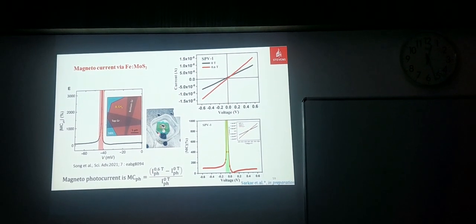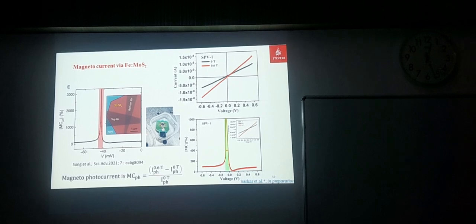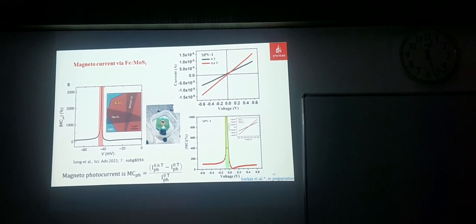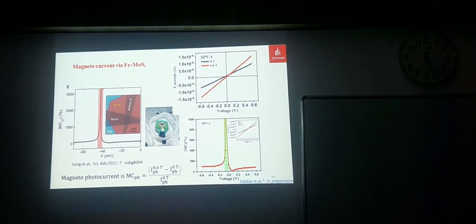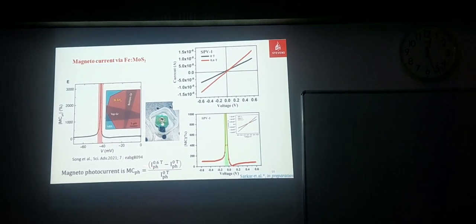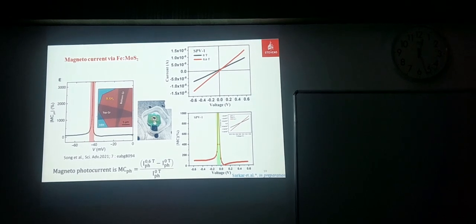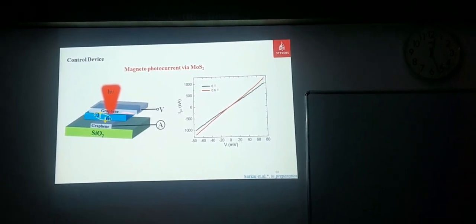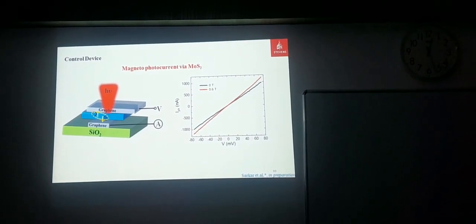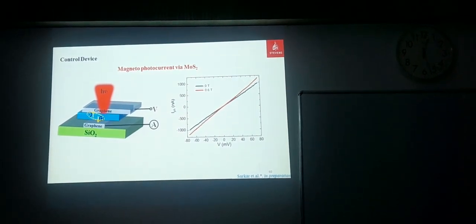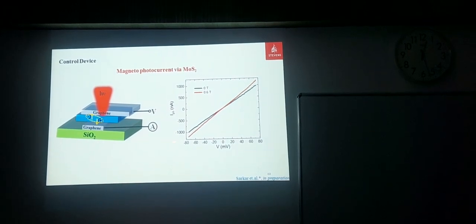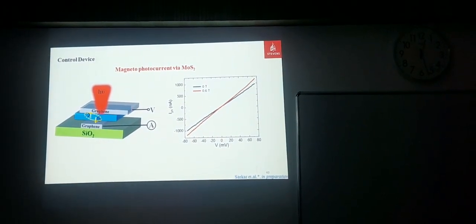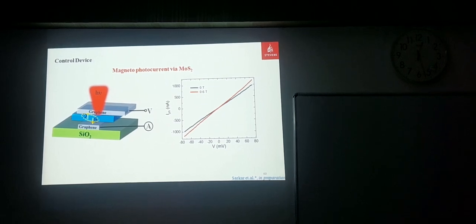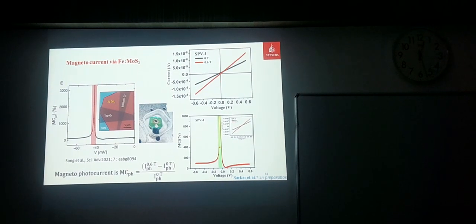Here you can see one of our devices which we mounted before loading the sample. I will come to the next slide on how we measure the system. We also did some optics in this system. I am not going to show details because this is not published yet. Here we did a control device, based on MoS2. It's a non-magnetic material, so you cannot see any change with the magnetic field, especially in the open circuit voltage of the system. That means our system is working well. Oh, I already discussed this.